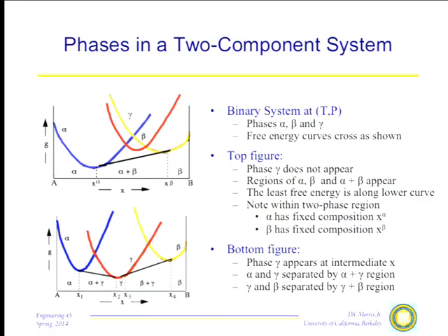That's how I could calculate the phase diagram, find the equilibrium phases at every temperature and composition if I knew these curves. Well, of course, in general, I don't know the curves, but what I do know is that curves exist, and therefore I can see the way phase diagrams should look. I'm likely to have a solid solution near both terminus, A and B. In between, I may well have two-phase regions. And within the two-phase region, as I move the composition through the two-phase region, I will change the phase fractions, but will not change the compositions of the two phases. They're fixed by the temperature.